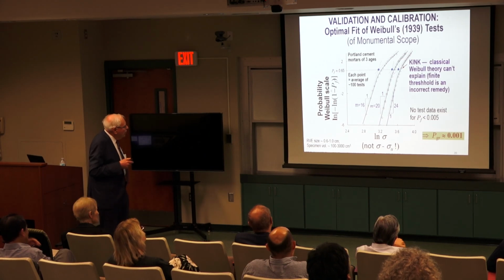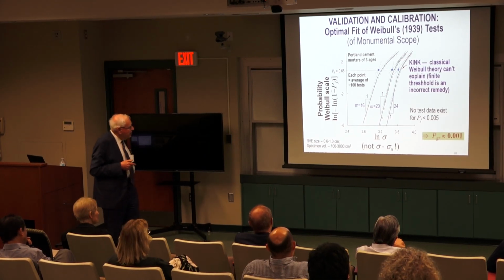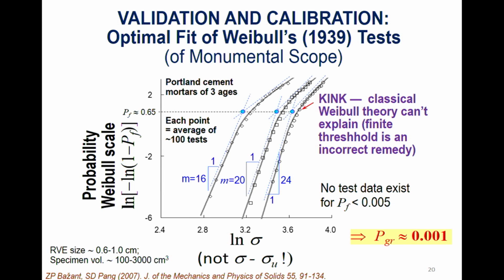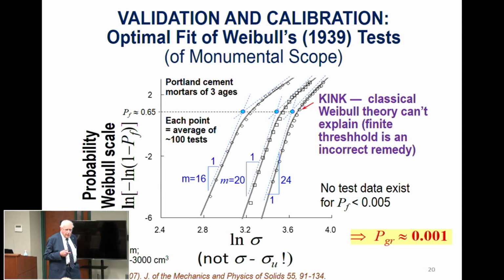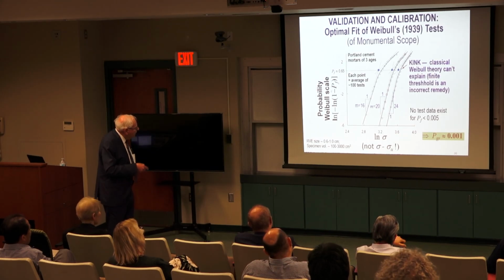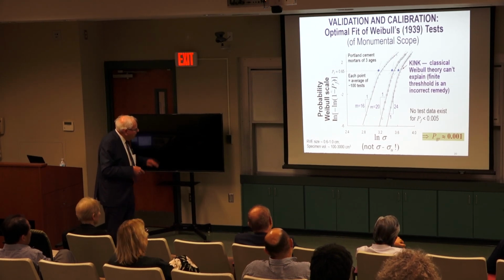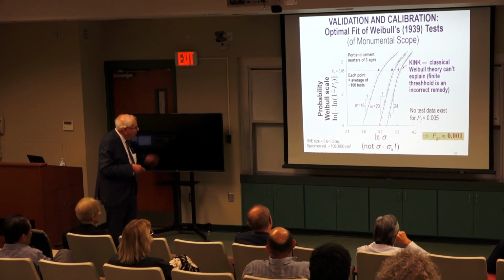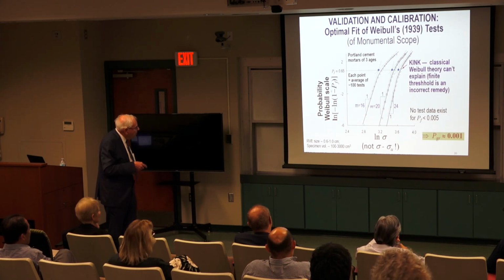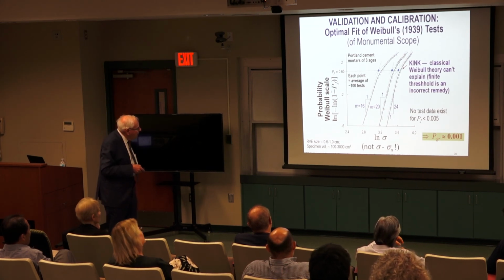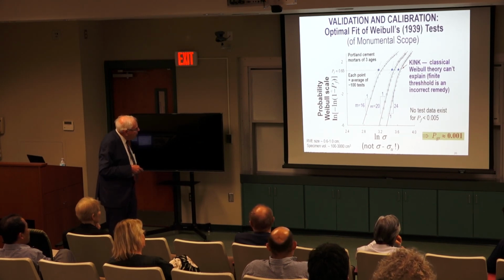So let me now show some typical test results. The biggest set of experiments, amazingly, was obtained in the 1930s in Stockholm by Weibull. He tested 10,000 specimens of concrete, more of steel, more of ceramics, and obtained these histograms. So this is plotted in Weibull scale. So Weibull is a straight line here. For brittle steel, for ceramics, you obtain straight lines only. But for concrete, this is concrete, he obtains these curves. And you see how amazingly smooth these histograms are.